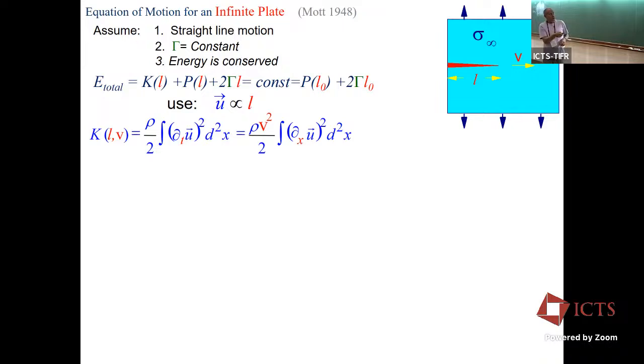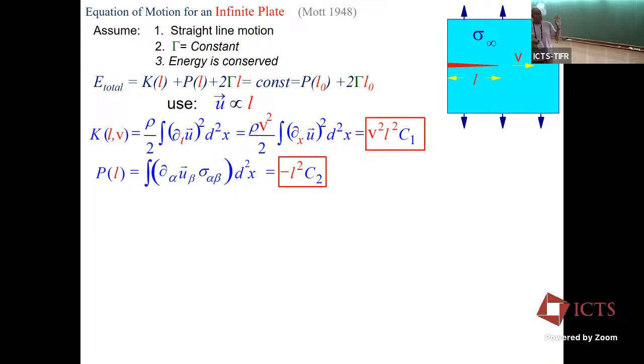And we're assuming that the crack is moving at velocity v. So instead of a temporal derivative, we'll replace it with v times a spatial derivative d/dx. And then we'll make a jump and we'll say, okay, this has to go like v squared, the speed, times L squared, because we have a quadratic expression in the displacement field u, so it's v²L² times some constant of integration.